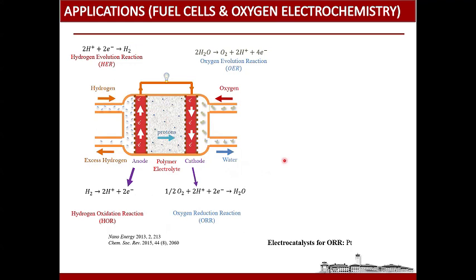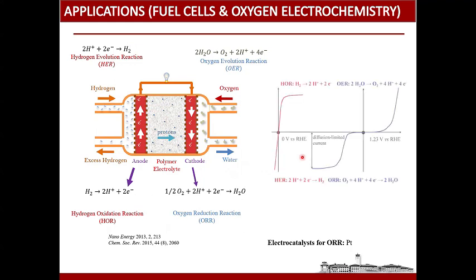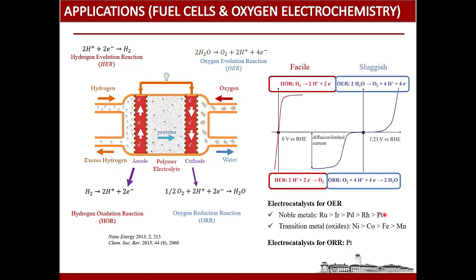And there are different catalysts used in these electrochemical processes, and these catalysts are generally noble metals, like ruthenium, iridium, palladium, rhodium, or platinum. For the oxygen reduction reaction, which is one of the main reactions in fuel cells, platinum is used, and these are all very expensive, and their abundance is low as well. So we should go to alternative catalysts like transition metal oxides. Some transition metal oxides work well for these catalytic applications, but still the efficiency is not as high as these noble metals. It is not as high as platinum or ruthenium or iridium for the oxygen evolution reaction.